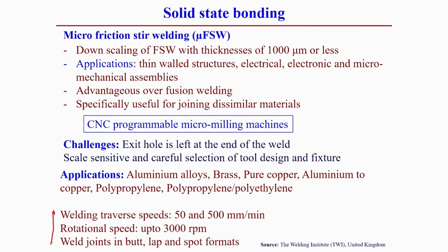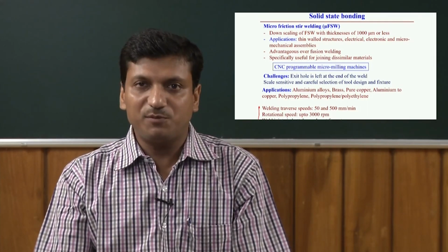If you see the typical parameters used for the friction stir welding process, first is the welding speed around 50 to 500 millimeter per minute, rotational speed at the maximum 3000 rpm, and weld joints can also be formed in the butt, lap, and spot formats. But micro friction stir welding is still in the developing stage, and work on other types of material and many dissimilar combinations of materials is still going on.